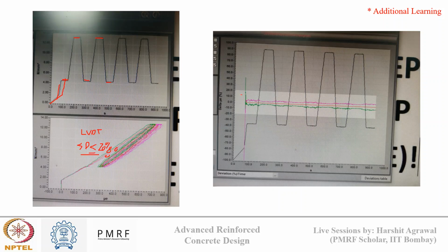You can see from here also the deviation between the red profile, violet profile, and green profile is within 10%. It is actually within 5%. So this means that the loading was proper, there was no eccentricity, and from the slope of this curve, we determine the MOE value. So this is how the MOE value is determined using static MOE in the laboratory.